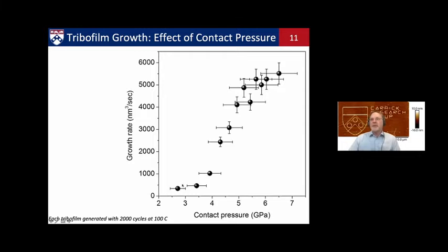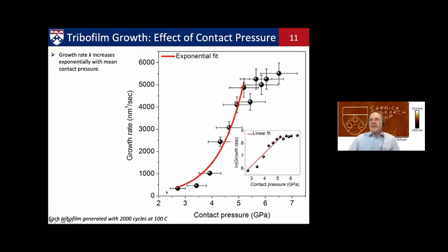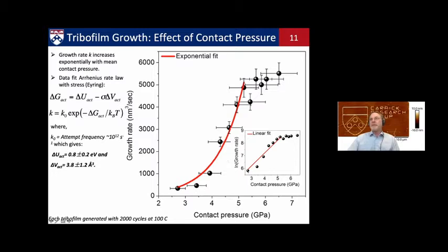So these are a series of experiments. Each one, the load is kept constant, and this is the initial contact pressure we apply based on using contact mechanics to calculate it. And what we see is as we increase the pressure, there is indeed a rapid increase in the rate of growth up to a point where it eventually doesn't increase much anymore. And if you plot on a log scale, indeed you see something consistent with a linear law using this Arrhenius or Eyring-like model, from which you can pull out an activation barrier of about 0.8 electron volts. That's reasonable for covalent bond-like interactions. And you can get an activation volume of a few cubic angstroms, which is reasonable for a molecular scale process.